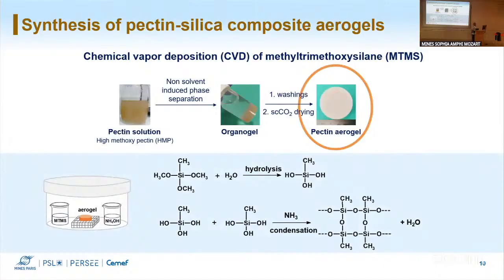Yes. So first for the temperature, even though it's below the boiling point, we still have the surface tension in the closed container, and we get the saturation of the vapors. So it can still proceed. There is this process also in the literature. It's feasible with the catalyst. Then why choose this? We tried to functionalize pectin with HMDS and graft, but it does not graft. And this was not even a vapor-solid reaction.